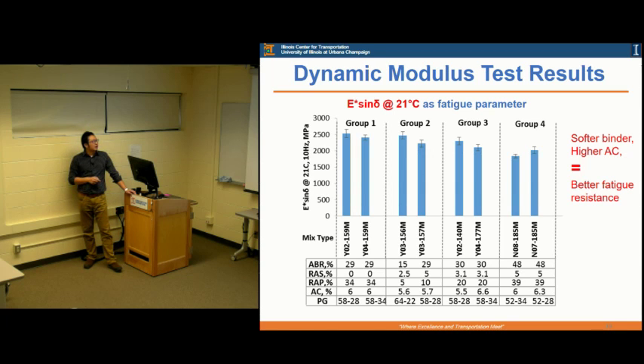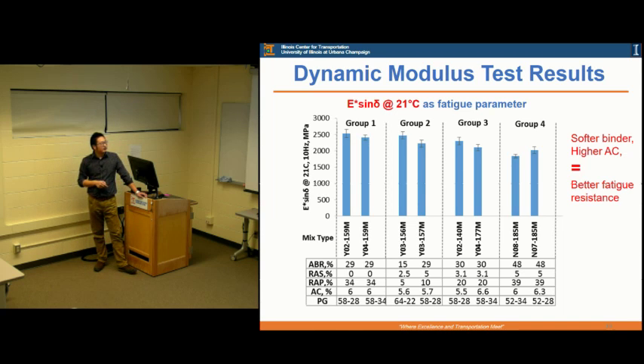And if you look at these two, it's the same way - even though the ABR is higher, you are using a soft PG, soft binder, so you get a better fatigue resistance. And also you get a higher AC.